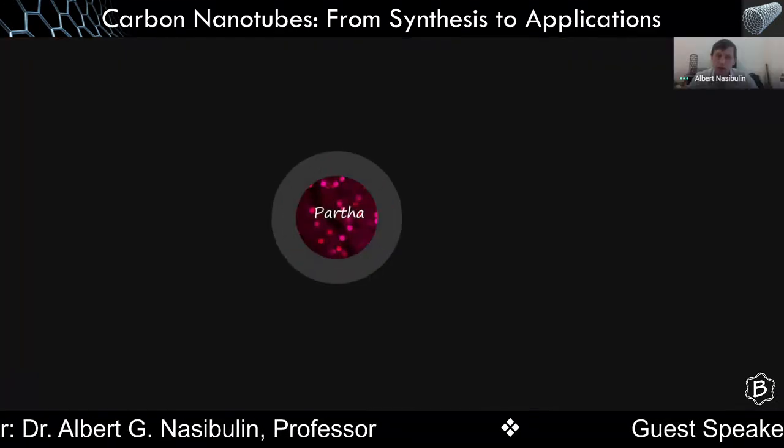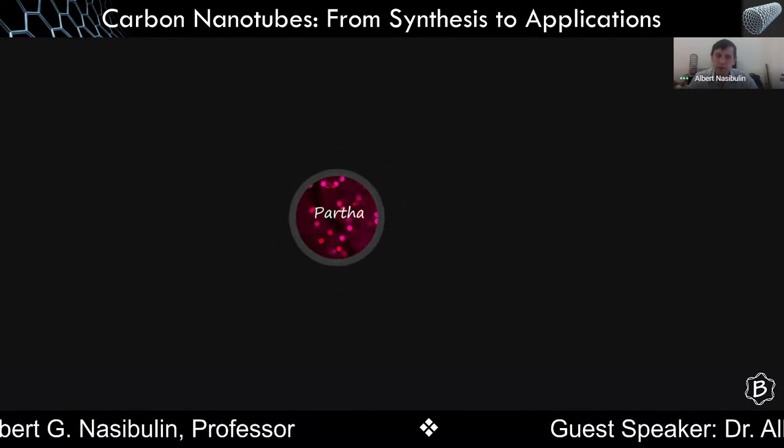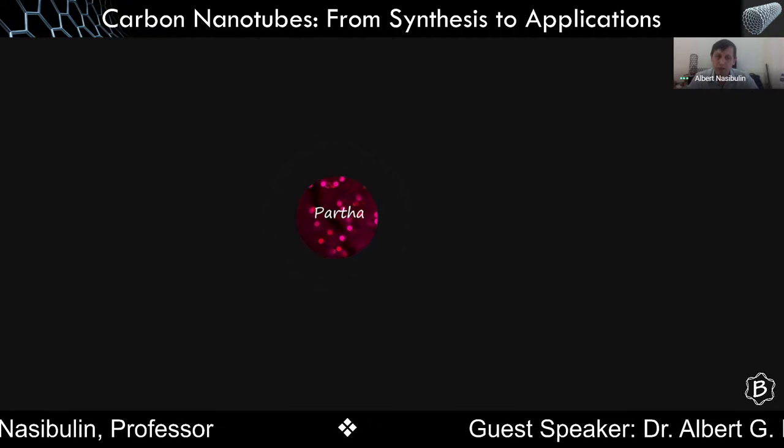The next question is, is it possible to synthesize carbon nanotubes using physical vapor deposition techniques? It depends on what the physical vapor deposition is. First of all, you need to provide the factors which you need when you grow carbon nanotubes. You need to provide a high temperature above 400 centigrade. At low temperatures, only with plasma enhanced CVD can you grow carbon nanotubes. Usually to grow high quality tubes, you need 800 to 1000. With a PVD, you could basically create the catalyst particle, but PVD alone wouldn't allow you to synthesize carbon nanotubes. Maybe you would be able to make a catalyst particle, a pre-stage, but not the growth itself.